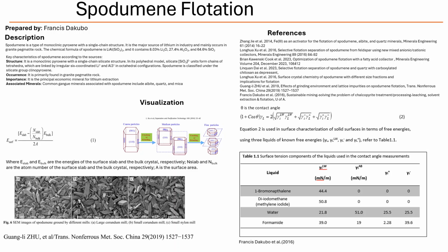Wow. What? It seems to be about tiny amounts of metal ions getting onto the spodumene surface during grinding. From the mill wearing down. Could be from the mill, yeah. Little bits of aluminum, iron, whatever the mill contains. Or it could be ions coming from impurities already in the spodumene crystal itself being exposed or mobilized by the grinding. We're talking Al, Ca, Mg, Fe, even Li ions. So the crushing machine literally becomes part of the surface chemistry.